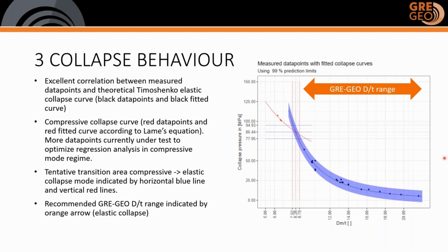That's the instability criterion for elastic collapse. And that follows the relation as described, for instance, by Timoshenko. The mode of failure in the transition area is uncertain. So I've indicated the transition areas by the horizontal and vertical lines. We used statistics to determine the transition area and decided that for the GRE-GEO guideline, we will limit the design to the elastic collapse region, indicated by the orange arrow in this plot.